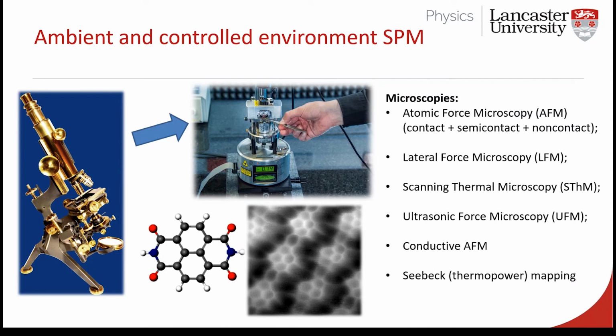Many different things with AFM. So we can measure not just that surface topography, but we can measure lateral forces. So we can measure friction in a junction. We can measure the thermal transport. We can measure the electrical transport. And also I'll say a bit about measuring the thermopower. There's a lot of interest in thermoelectric energy generation from different materials and different structures. And that's a capability we've also been developing.